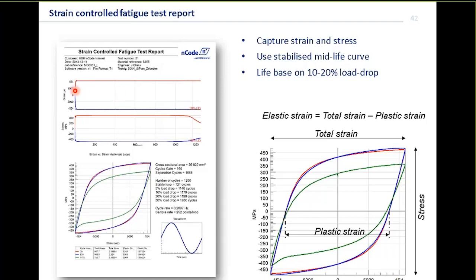So at the beginning here, we can see that we've got a very quick soft start effectively, so that control system keeps up with what we want. And then it keeps perfectly straight, because we're in strain control. The controller is controlling the strain. Over here though, we can see the result from the load cell. So first of all, it stabilizes. Sometimes we see some plastic hardening or softening occurring here in some plots and some materials. We then stabilize, and then what we see here is a load drop.